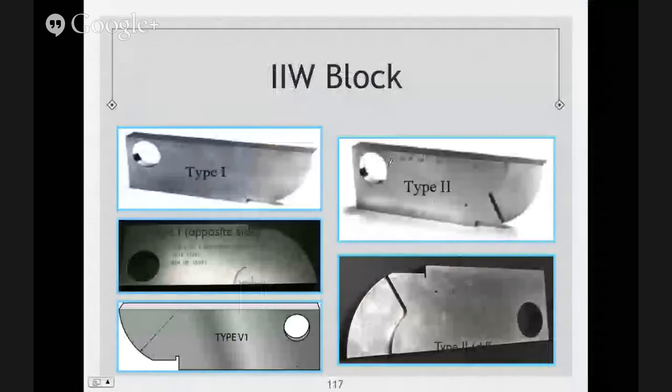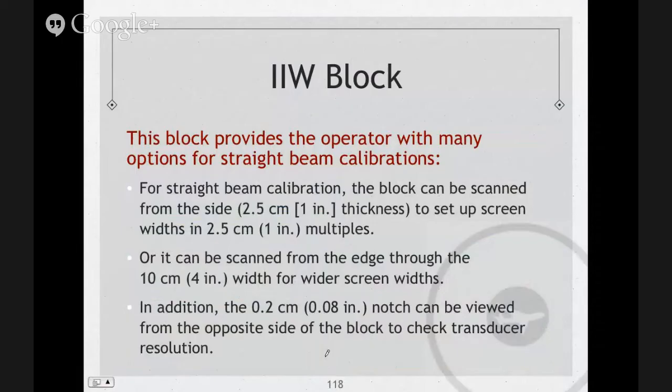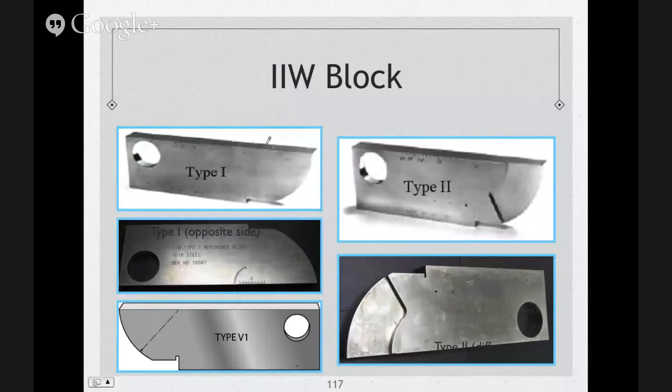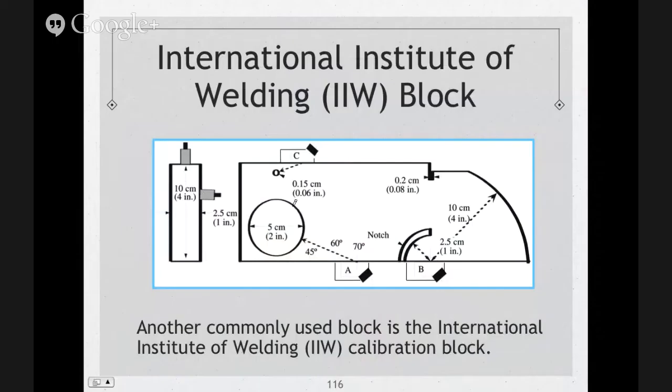Yeah, and you can check it from the bottom here, shooting to that piece of plexiglass, okay? Or your side hole right here. This block provides the operator with many options for straight beam calibration, right? So for straight beam, you can measure the thickness, which is 1 inch right here, okay? And on your screen, you could actually see